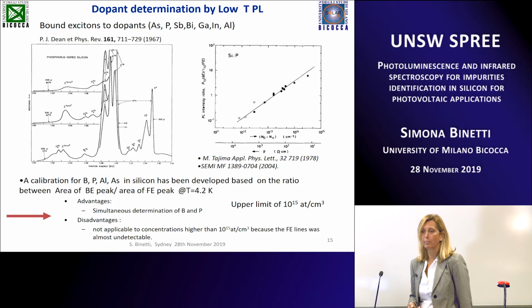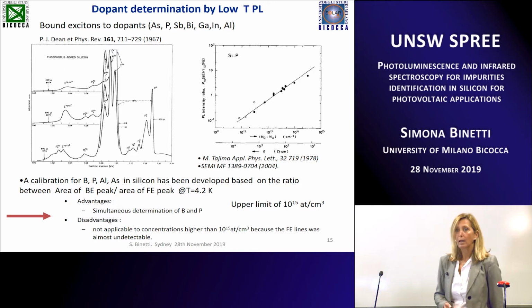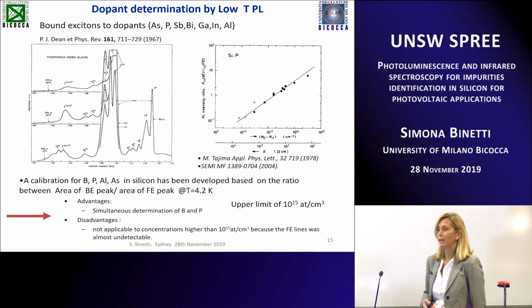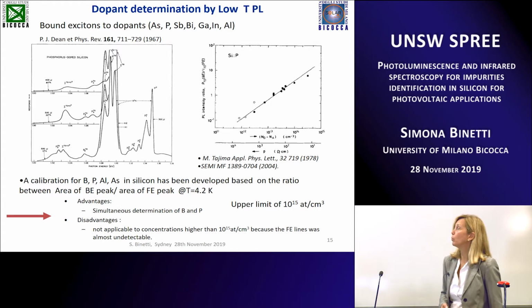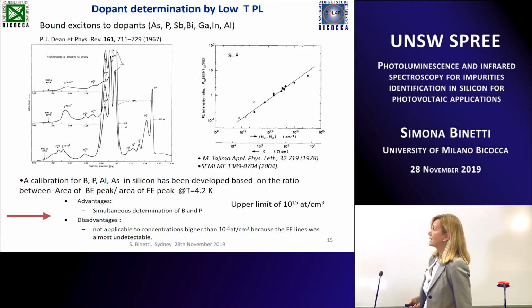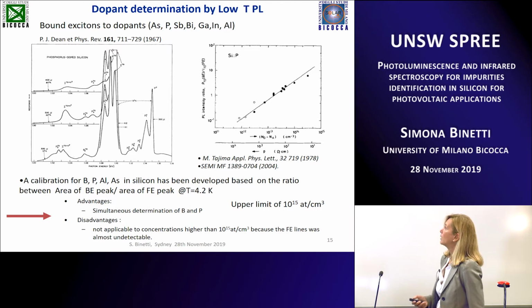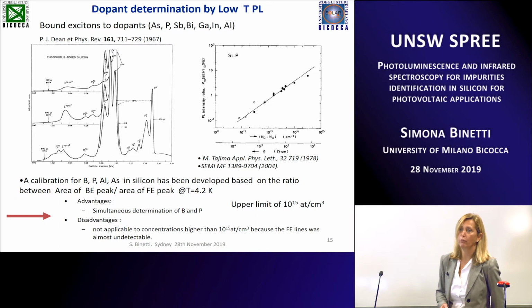Photoluminescence is able to detect the dopant independently of the concentration by detecting the bound exciton lines related to different types of dopant. So each type of dopant can be seen by checking the bound exciton lines of the dopants. This, of course, must be done at very low temperature, at 4.2 Kelvin. But it is the first work in which you can have quantitative information, very accurate, by photoluminescence.